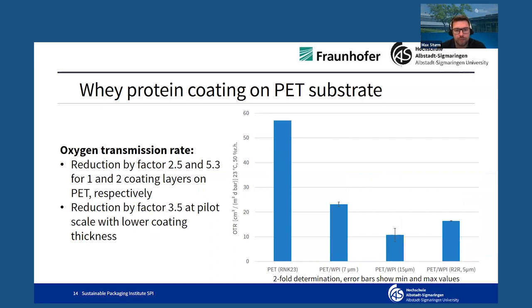Next, we also applied the whey protein coating on PET substrates, as this is also a very important substrate for food packaging applications. Here you can see also a decrease of the oxygen transmission rate to about 23, down from 58 of the uncoated film, and even a further reduction with thicker whey protein coating to approximately 10 cubic centimeters per square meter day bar. And similar to the PLA, here we also found comparatively better results at the pilot scale due to the more homogeneous coating application due to the different coating processes.